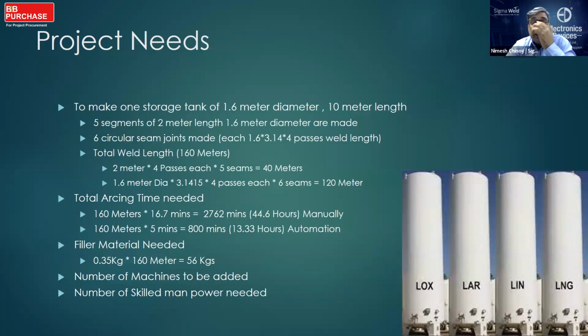Let's consider one project for you. If you were to make a storage tank of 1.6 meter diameter and 10 meter length, as you see in the bottom figure, you would have 5 segments to weld of 2 meters length each and 1.6 meter diameter. This means you would have 6 circular seams to be welded with a total weld length of about 160 meters. And you would have 2 meters into 4 passes each, as we discussed before, for 5 seams. This gives you 40 meters of weld length on the long seam.